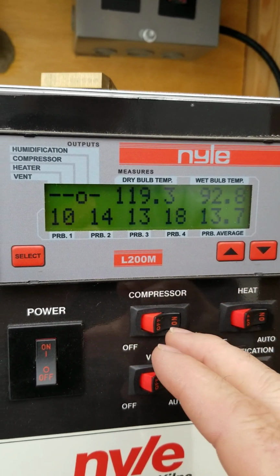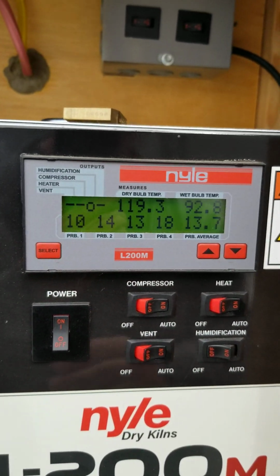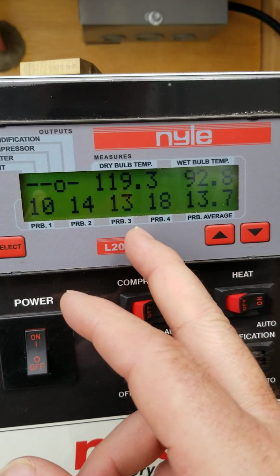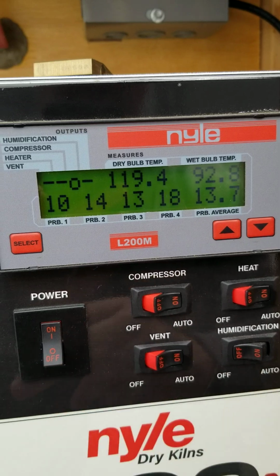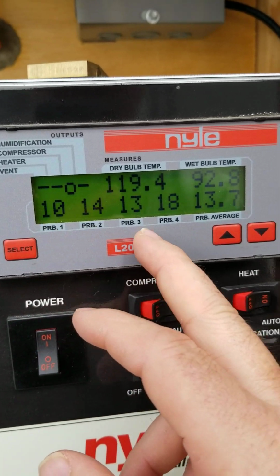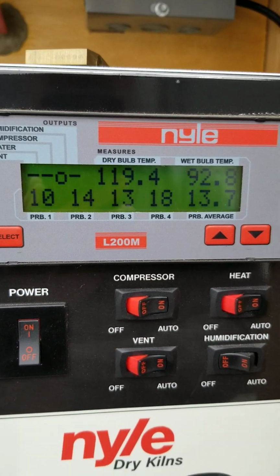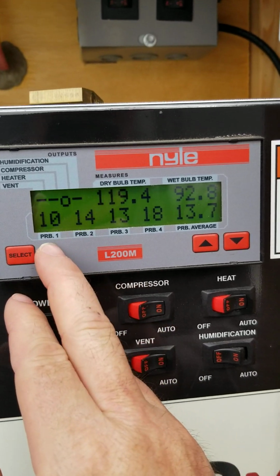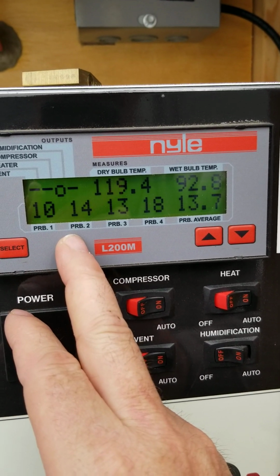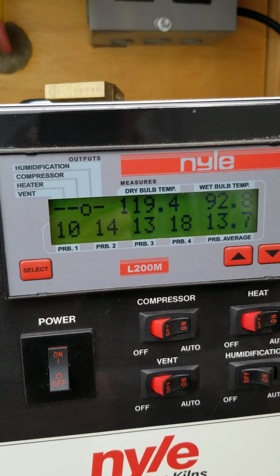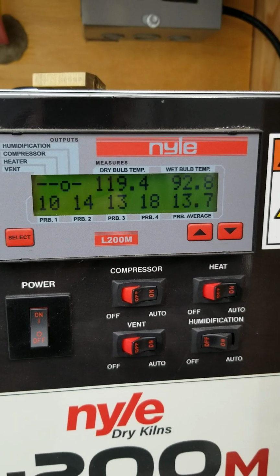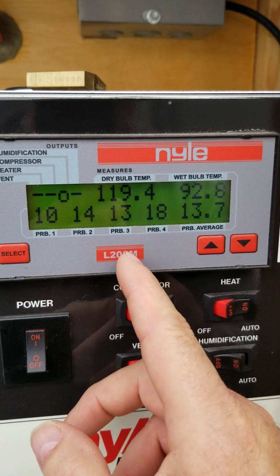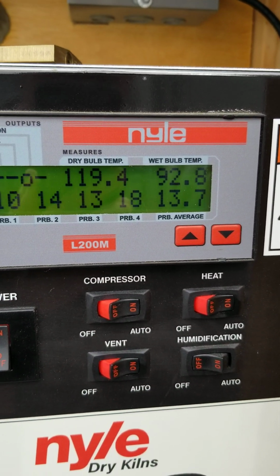And you can see now that the moisture has come down. It's equalized pretty good. We're still a little bit high on one of the hickories, but we're at 10, 14, 13, and 18, which is getting pretty close. So these two here, probe 1 and 2, are both in the maple, and probe 3 and 4 are in the hickory.